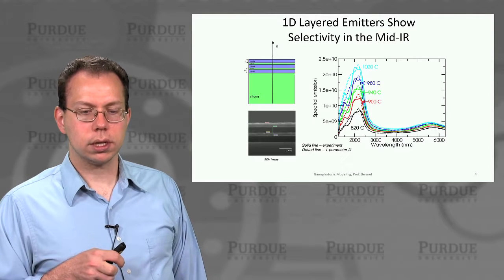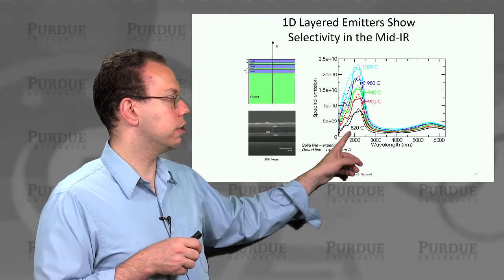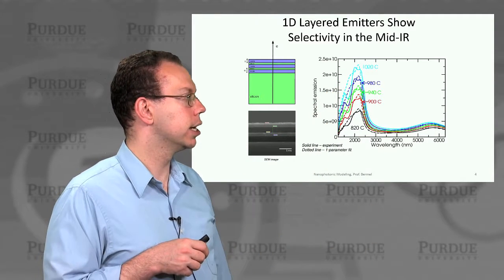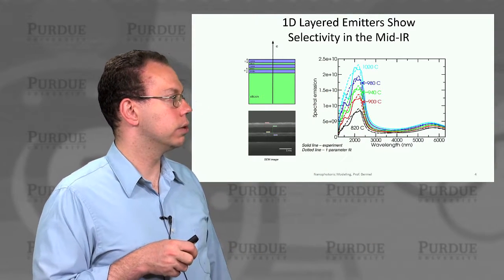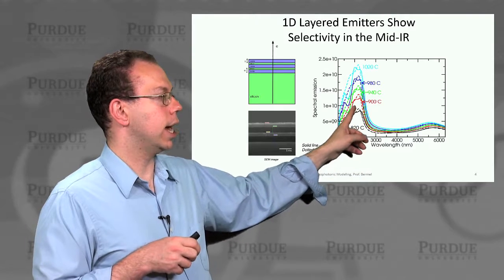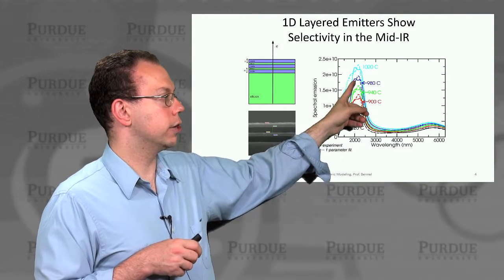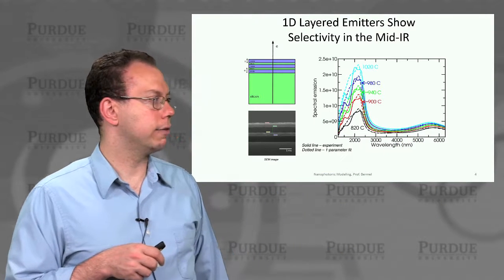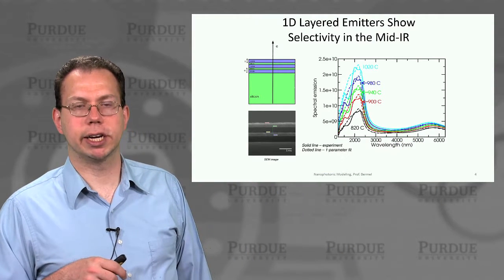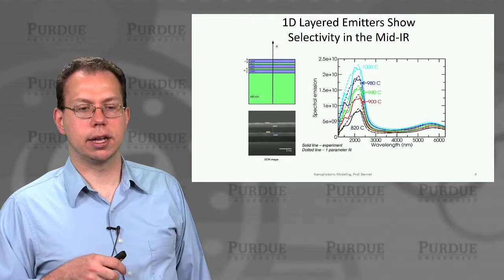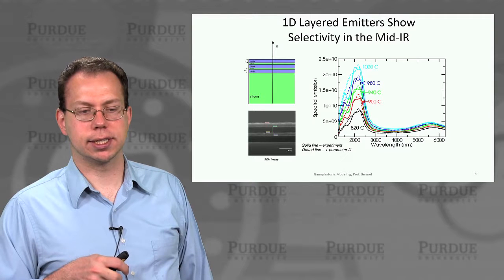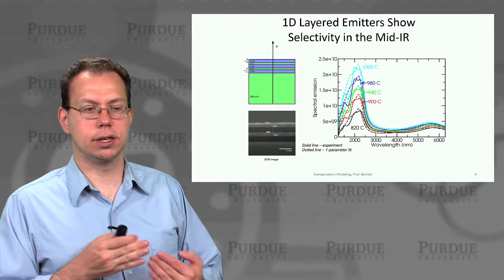And so this is basically showing that as you go from a temperature of 820 degrees up to 1020 degrees, the spectral emission will increase very rapidly at wavelengths around 2 microns. But at the same time, at longer wavelengths from about 2.5 up to at least 6.5 microns, as measured in FTIR, you have a much more modest increase in emission, which is consistent with having these two regimes.